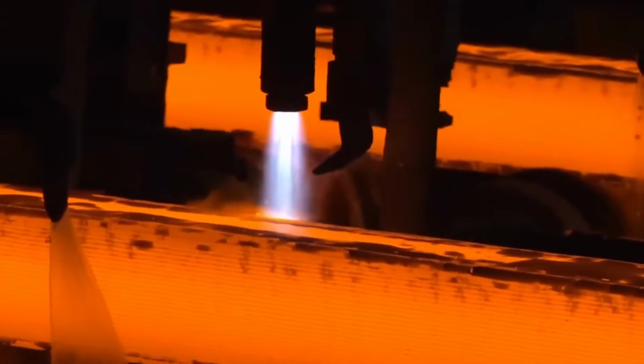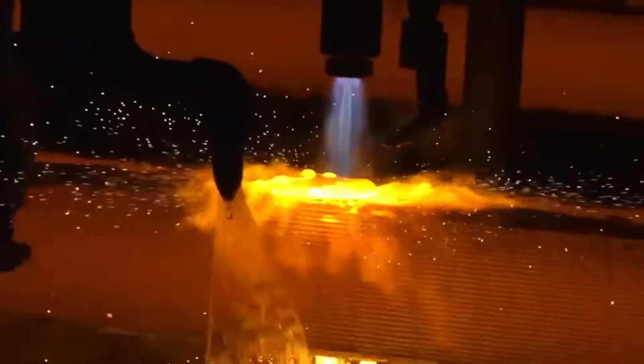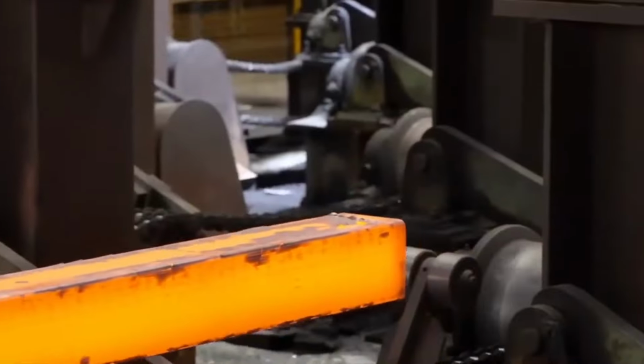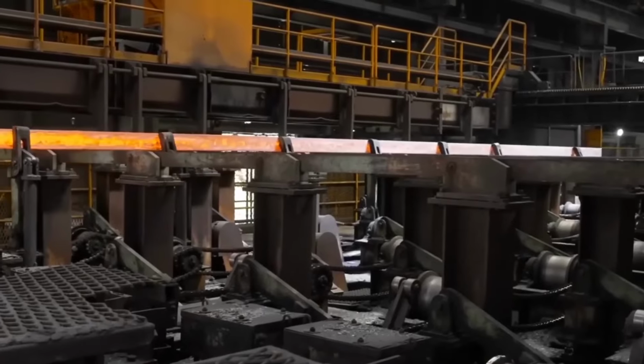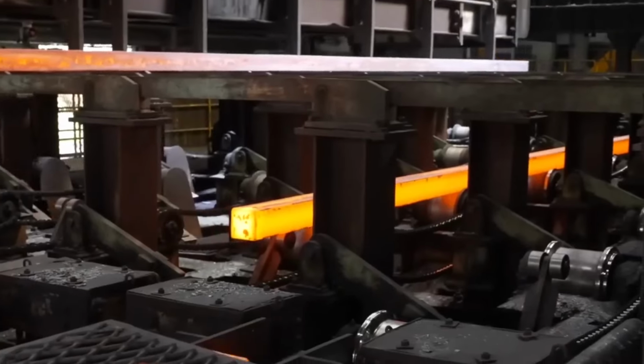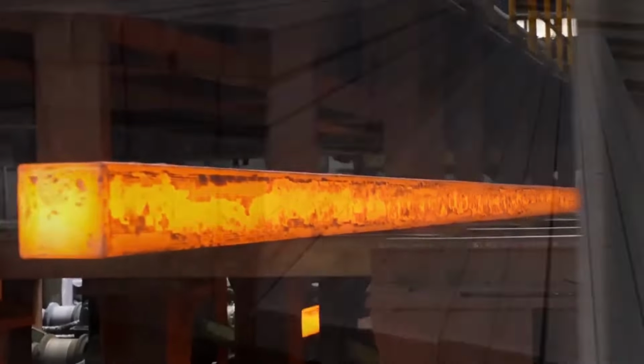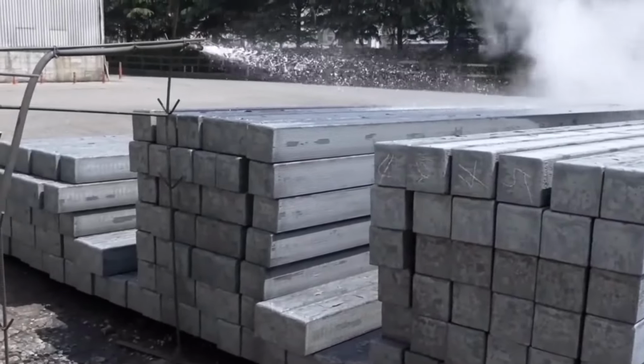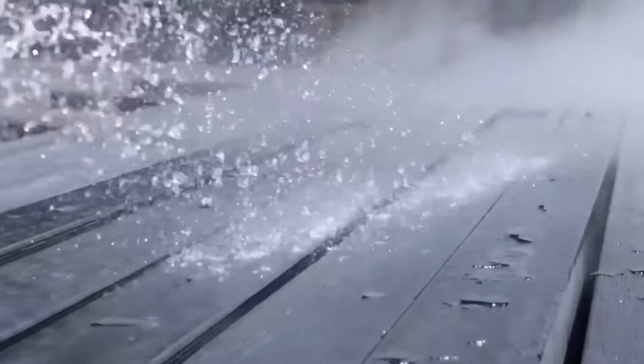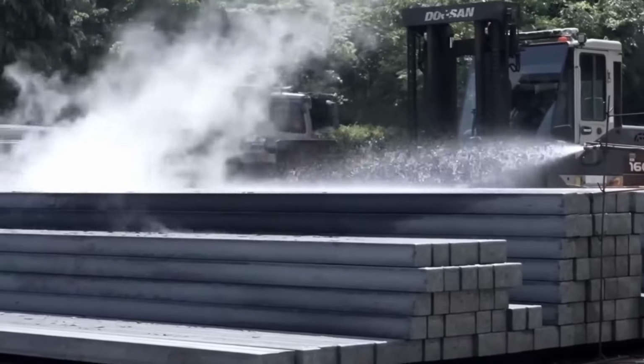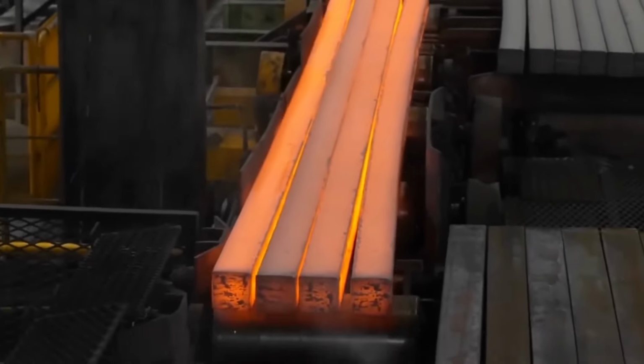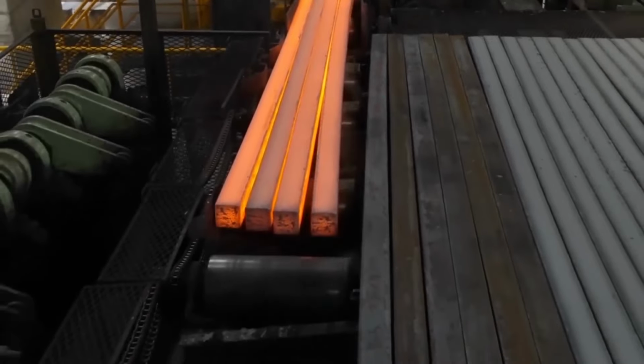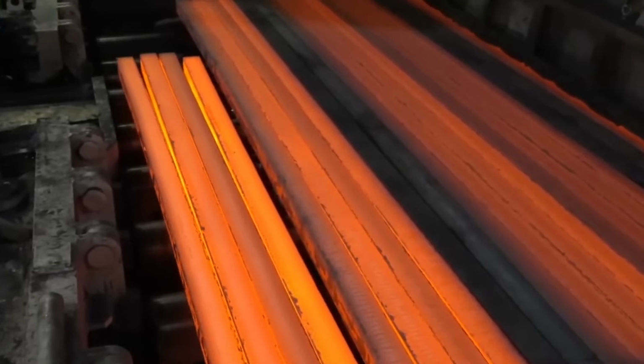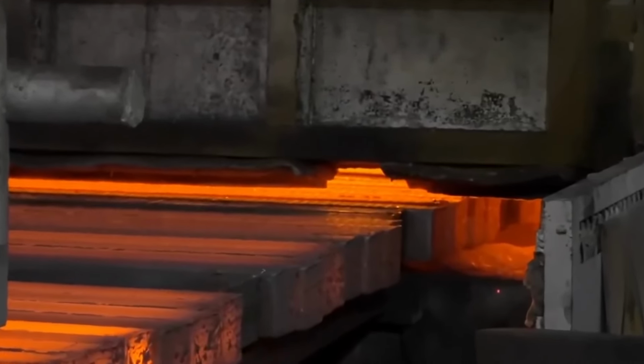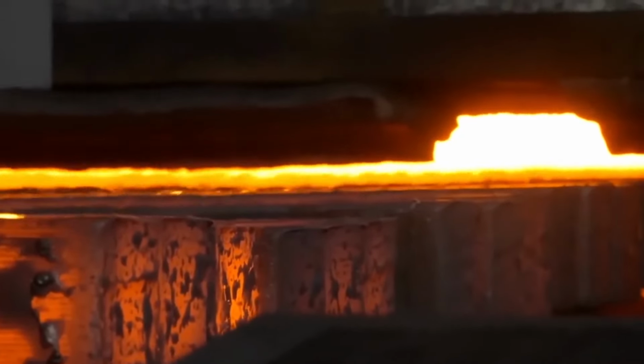Most factories today use continuous casting because it's faster, more efficient, and reduces waste. Instead of pouring molten steel into large molds, letting it cool, reheating it, and then shaping it, like the old ingot method, continuous casting keeps the steel moving, saving energy and preventing defects. Molten steel flows through water-cooled copper molds, which help it solidify quickly. As it cools, it slowly transforms into long rectangular billets, thick slabs, or cylindrical blooms, depending on what it will be used for. The glowing hot steel bars come out in a semi-solid state, firm enough to hold their shape, but still soft enough to be molded.